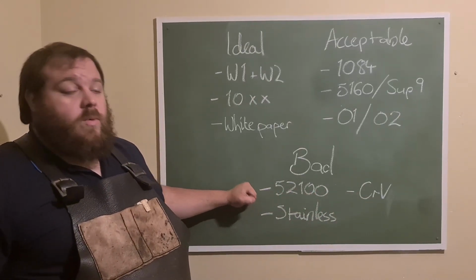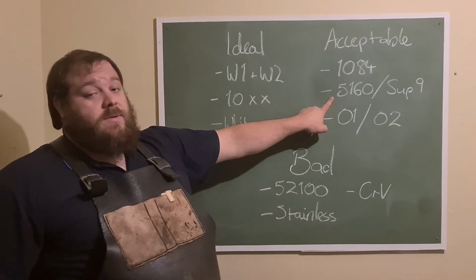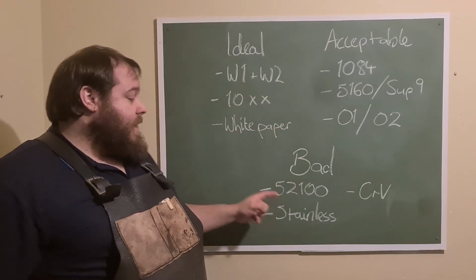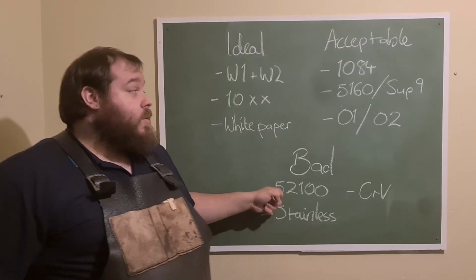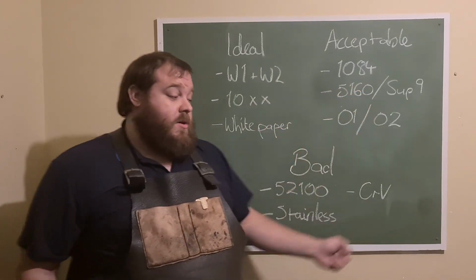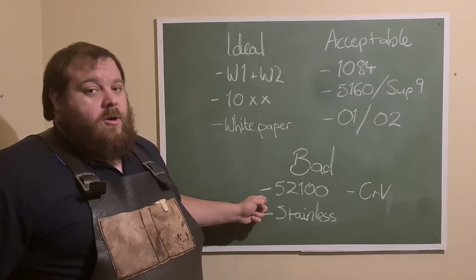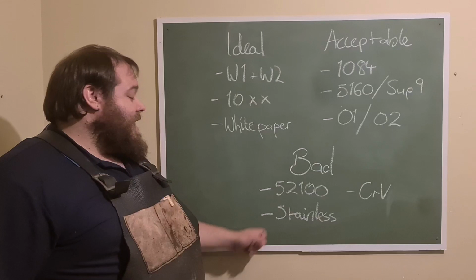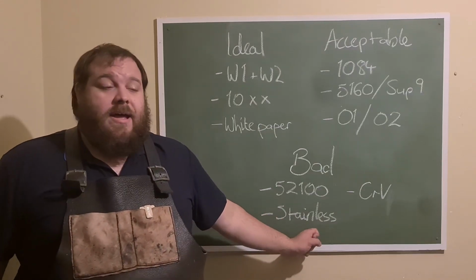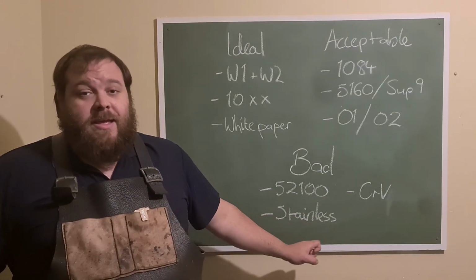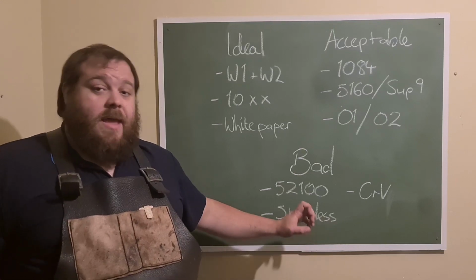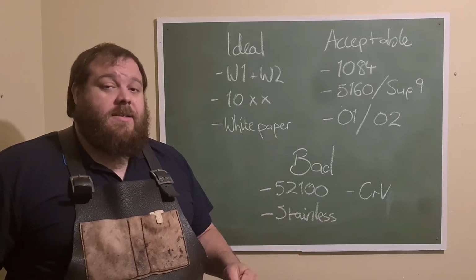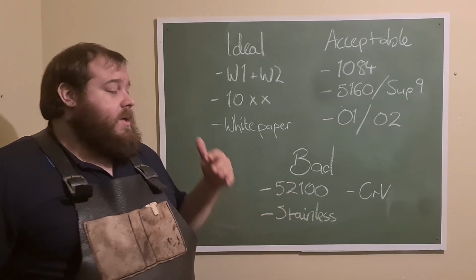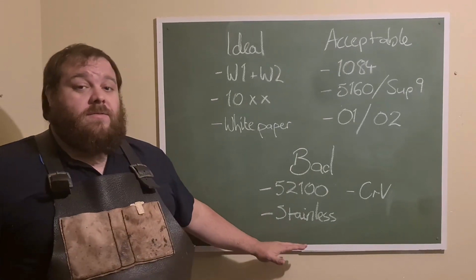52100 bearing steel will take a straight line Hamon, much like 5160, but again, will not have the activity, and it won't even have the activity of 5160 because it's got a lot more chromium than 5160 does. And anything that is stainless has way too much chromium. The depth of heat treatment and the heat treatment requirements for stainless, because you have to soak it at temperature, means that you will not achieve a Hamon in stainless.